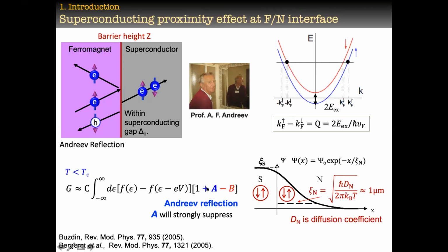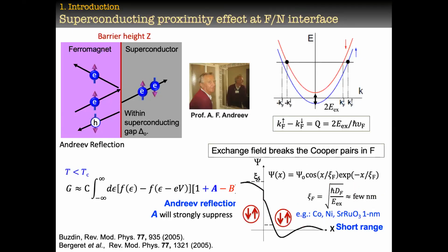So in that case, first of all, the conductance within the superconducting state in case of the ferromagnet will reduce. The second thing, the exchange field means the spin polarization. So we know that in a ferromagnet, the spins must be aligned. So what that would do is induce these Cooper pairs in the ferromagnet within a very, very short length. Because this time, the induction length depends on the exchange field. So it will be not more than a few nanometers. For example, in cobalt and nickel or strontium ruthenate 113, it will be just about 1 nanometer. It's a short range.